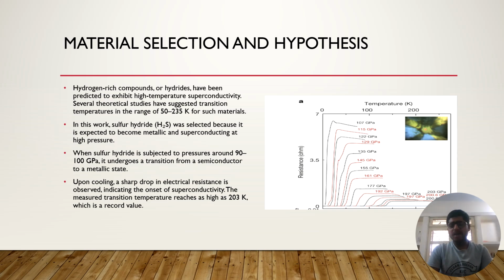Under high pressure, around 90 to 100 gigapascal, sulfur hydride undergoes a transition from a semiconducting state to a metallic state. This transition significantly enhances the density of states and electron-phonon coupling. Upon cooling, the electrical resistance drops sharply, indicating superconductivity. The transition temperature reaches around 200 Kelvin, which is exceptionally high and makes a major breakthrough.